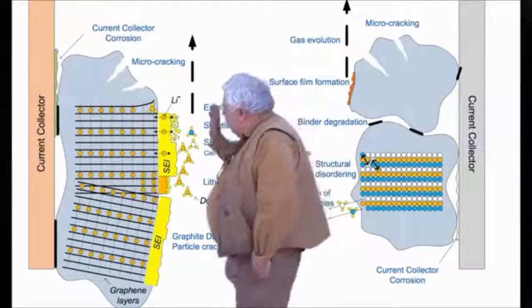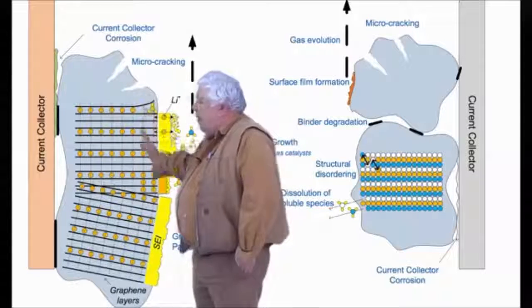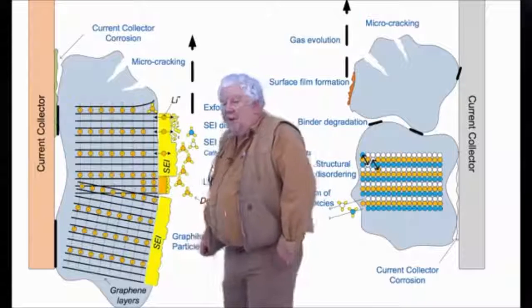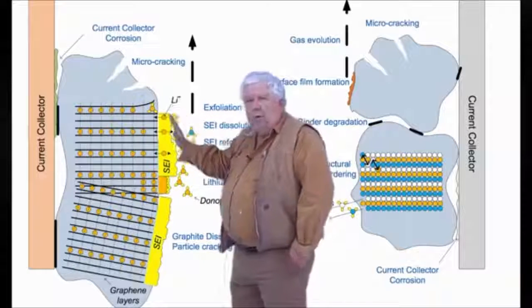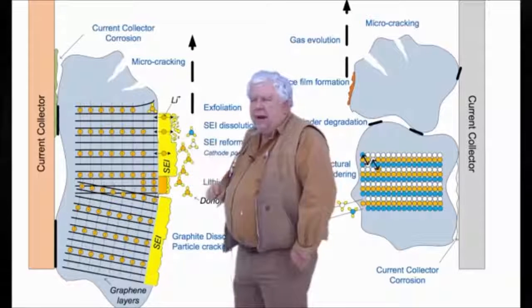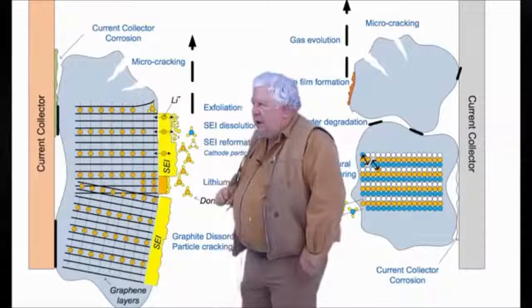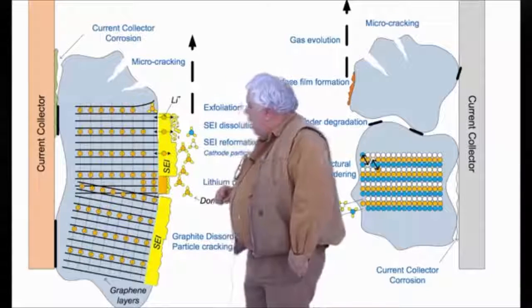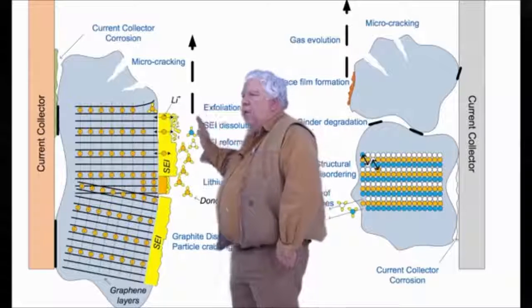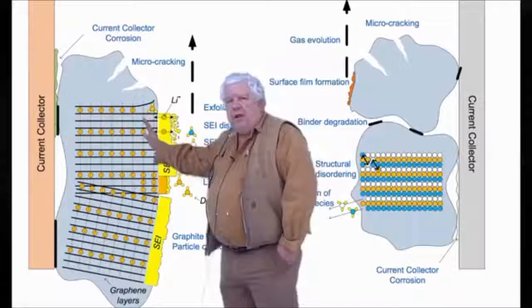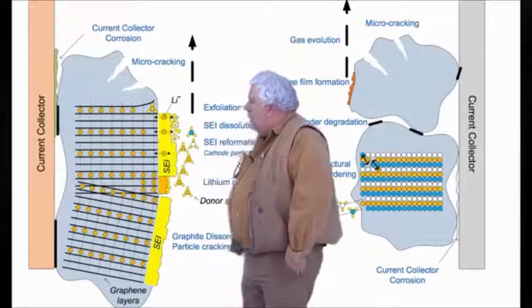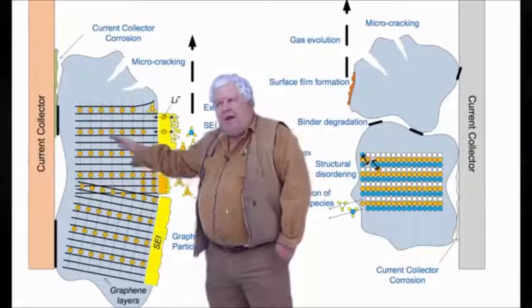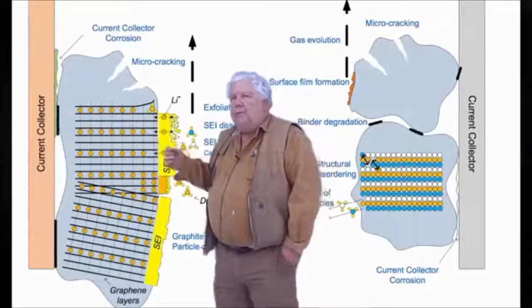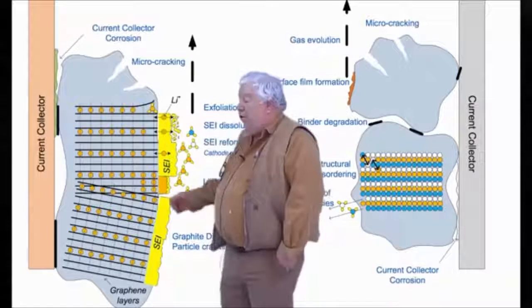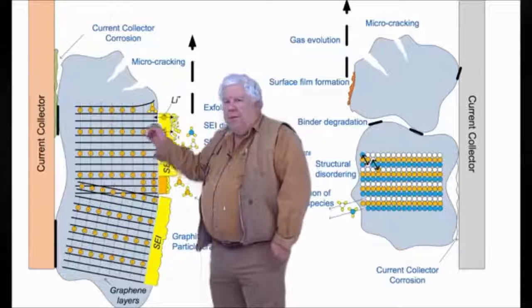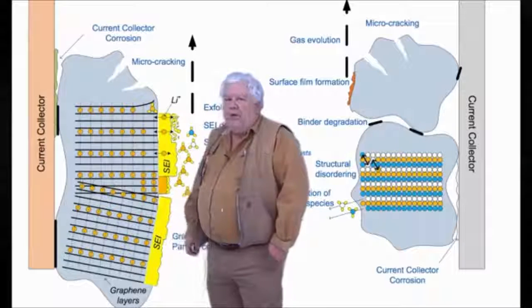As this thing charges, the first couple of times, this SEI layer forms. Well, it's got some unique properties. It kind of glues all the carbon together, which does get about a 10% volumetric expansion and contraction during intercalation and deintercalation. But more importantly, the organic molecules in the electrolyte cannot pass through the SEI layer at all. They just can't do it. But the lithium ions can. Now, they have to kind of tunnel through there, and so the SEI layer becomes kind of a function of our DC impedance or resistance of the battery itself, because the lithium ions have to migrate through that SEI layer.